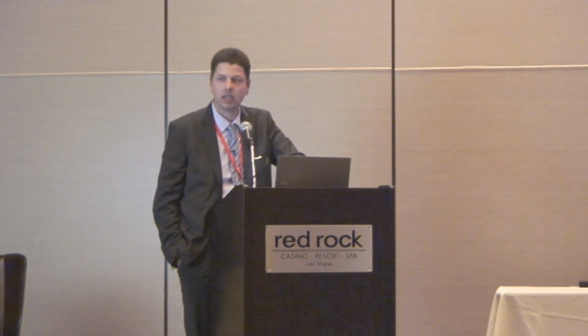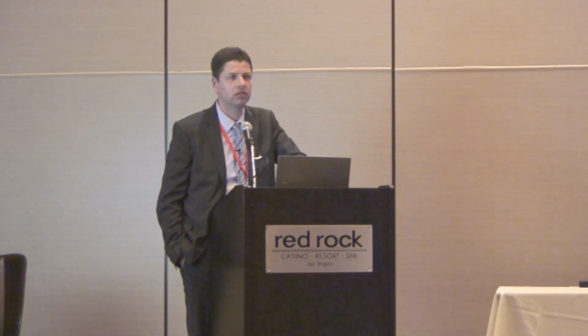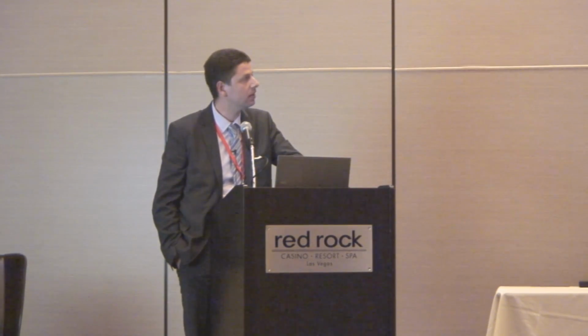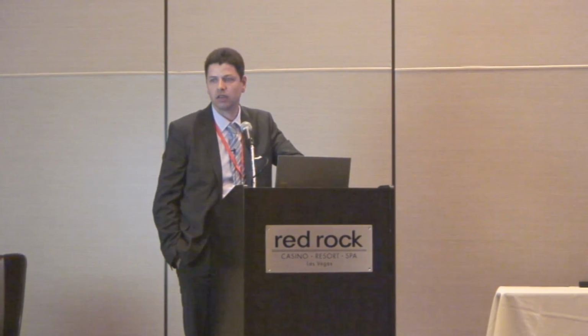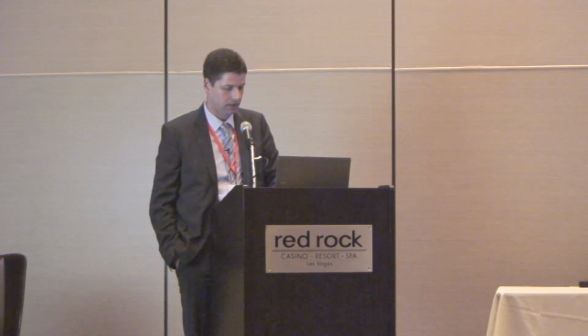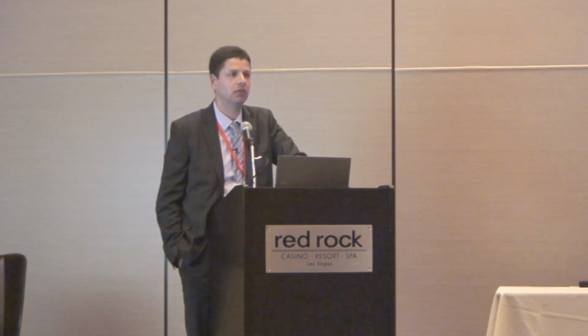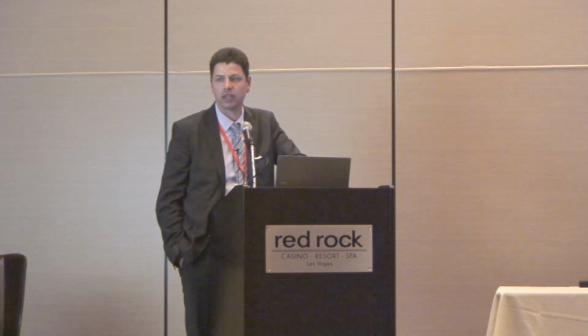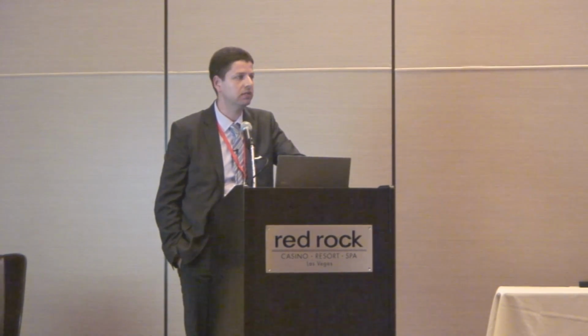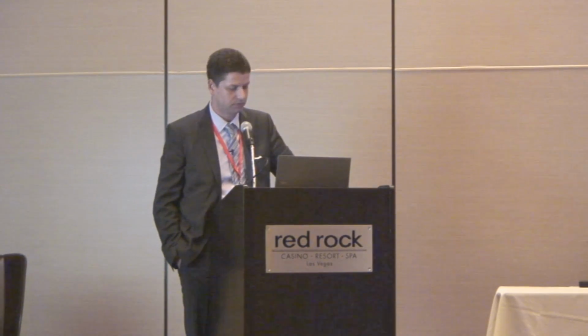What are the results for the sandwich brazing alloy? There we could not find a big influence of the gap size, but we could find a difference depending on the sandwich alloy composition. And the results we found in the real tests could again be found in the simulation. So we can say for the sandwich brazing alloy, there is not a big influence of the gap size. The strength of the final part depends mainly on the composition of the interlayer which is used.